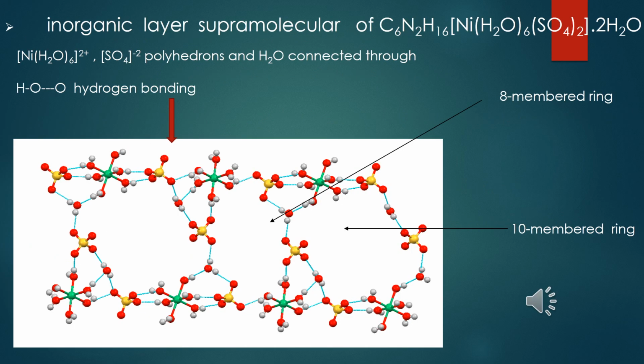The nickel hexaaqua octahedron, the sulfate tetrahedron, and the free water molecules are connected through O-H...O hydrogen bonding, giving rise to the inorganic anionic supramolecular layer, which contains 8-membered rings and 10-membered rings.